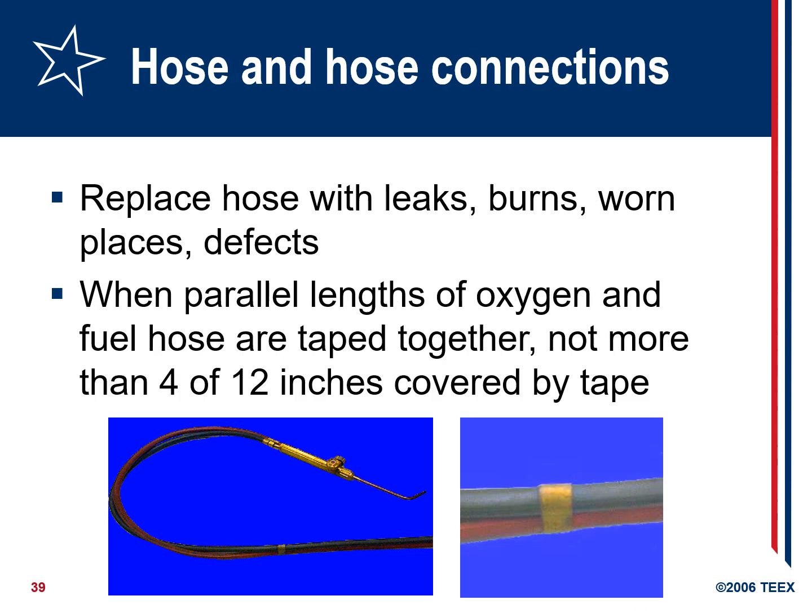Hoses and hose connections with leaks, burns, worn places, or defects must be replaced immediately. When parallel lengths of oxygen and fuel hose are taped together, not more than four inches out of every twelve inches should be covered by tape.